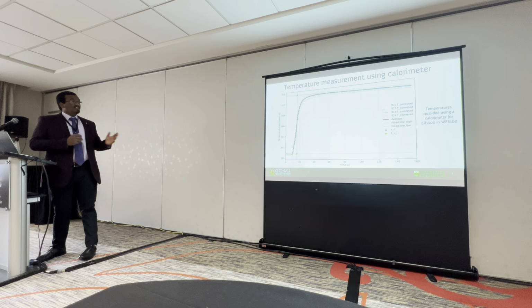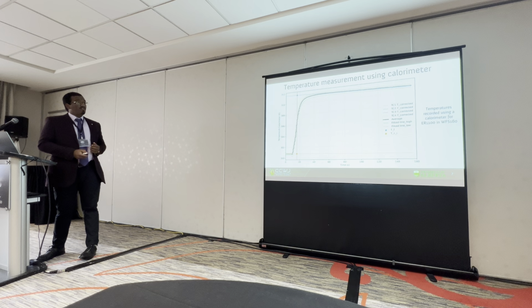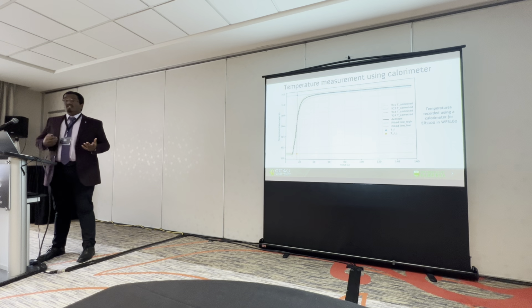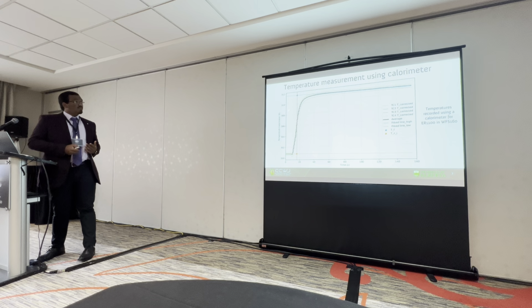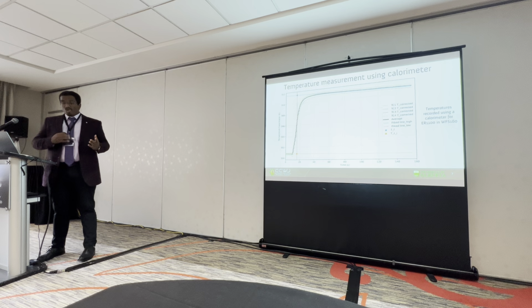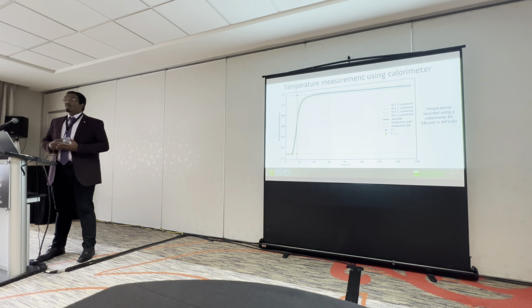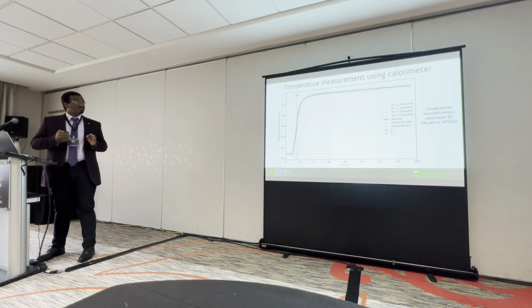And so this is just an example for ER1100 at wire feed speed 160, to show that we also account for the heat losses, and we use a temperature which is a very good approximation of the temperature of the calorimeter.